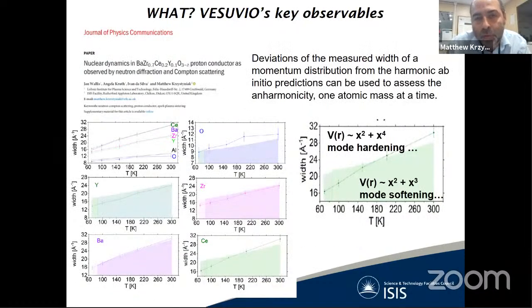What about using your lattice dynamics, even if it doesn't match your experiment? What can we tell from this mismatch? Another example of profiting from the fact that you have a benchmarking calculation and your experiment is actually not exactly following it, you can still learn from it. And this slide shows the mass-resolved study of nuclear quantum effects in a proton conductor, which contains barium, zirconium, cerium, yttrium, and oxygen. And in those slides, I have shown the measured versus harmonic lattice dynamics simulated width of momentum distribution. So you could translate it into the magnitudes of nuclear quantum effects of zero point energy. And you can see that in some cases, the experiment is above, in some cases, the experiment is below the values predicted by lattice dynamics.